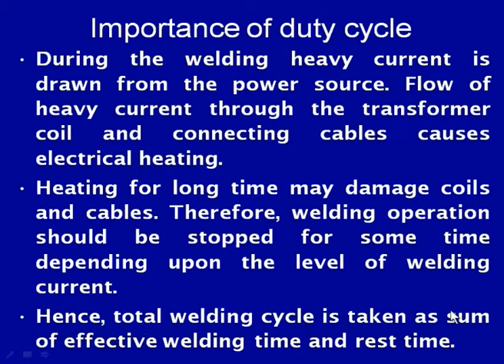Hence, the total weld cycle is taken as the sum of the effective weld time and the rest time. In the effective weld time, we actually draw the current. In the rest time, there is no current drawn, but whatever electrical resistance heating has been done, that heat is lost to the surrounding and to the cooling medium, so that the temperature of the coils and cables can be maintained.